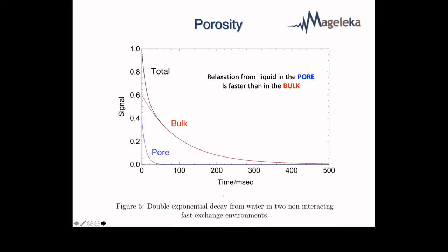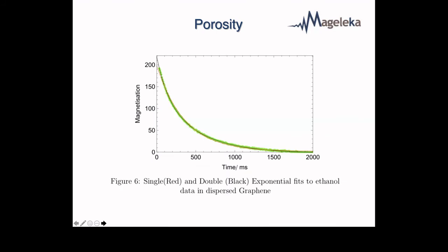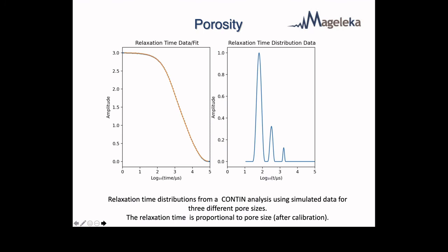So this is just some simulation data. This is a system where you've got pore water and bulk water, and this is the water in the pore, this is the bulk water, and this is the combined result. And if you then try and fit that data, so you do the NMR experiment, that's the green dots, and you try and fit it to a single or a double exponential, then you can learn about the two different environments, the bulk water and the surface water. You can do much better than that.